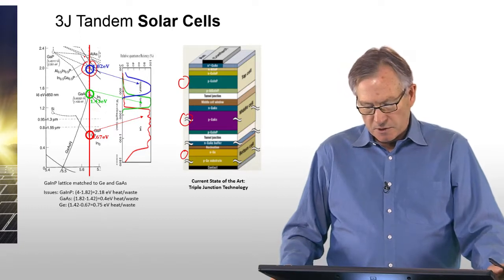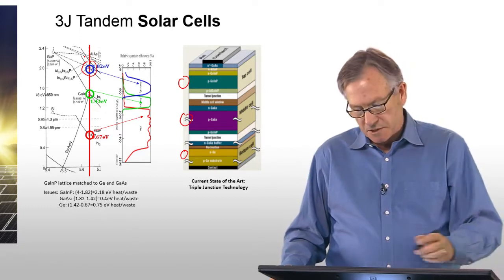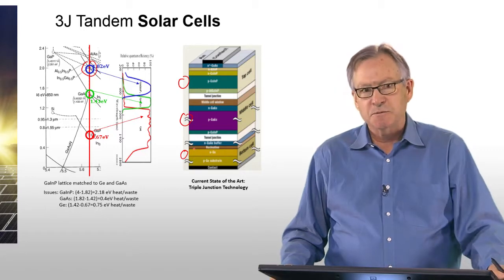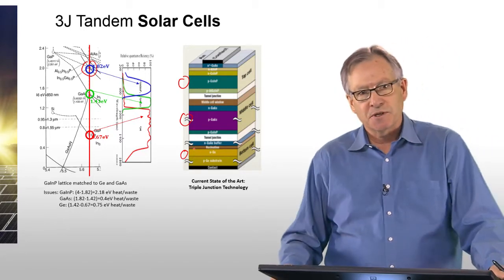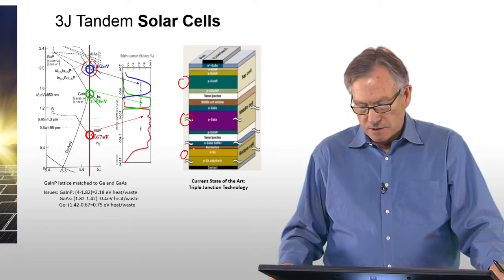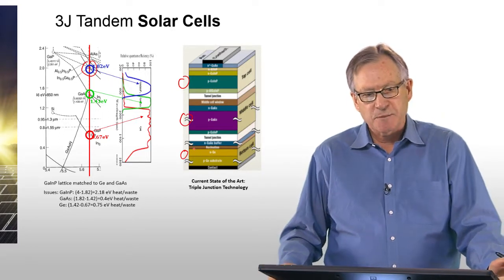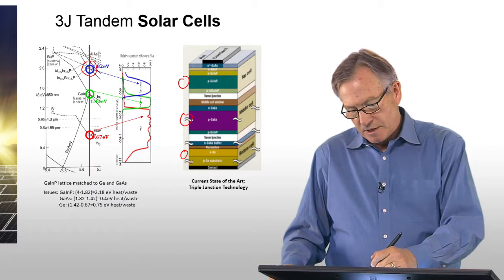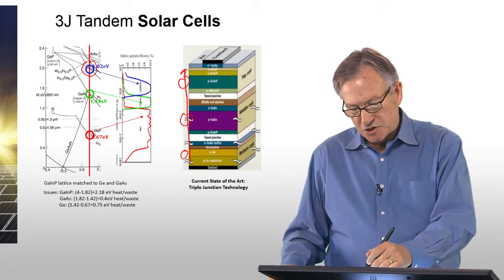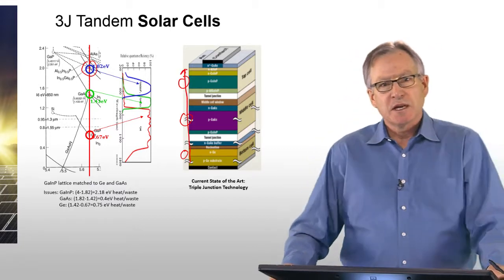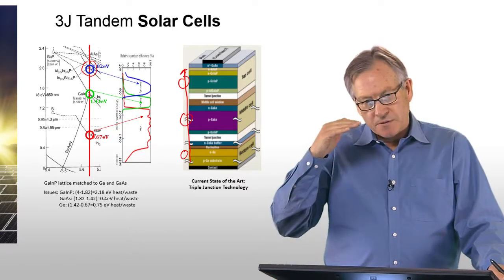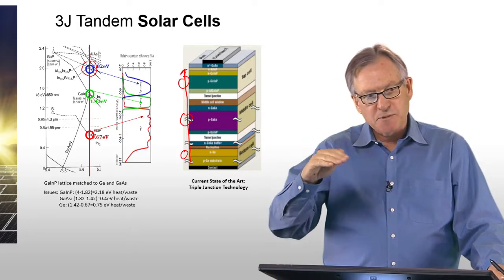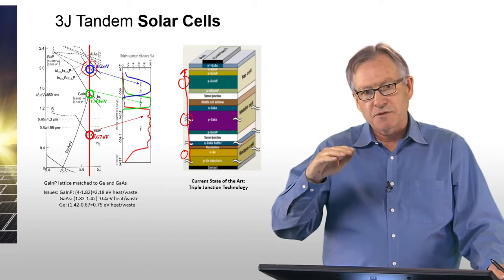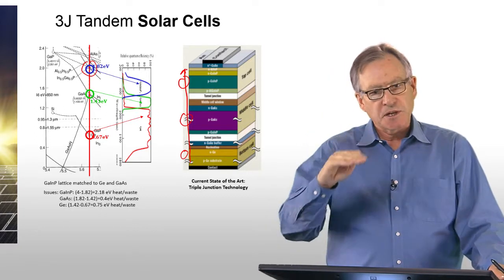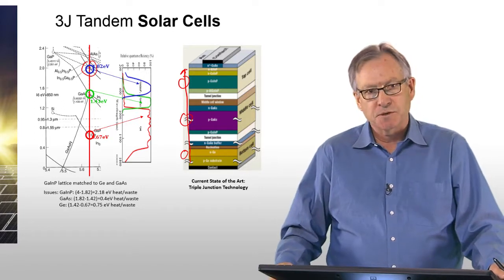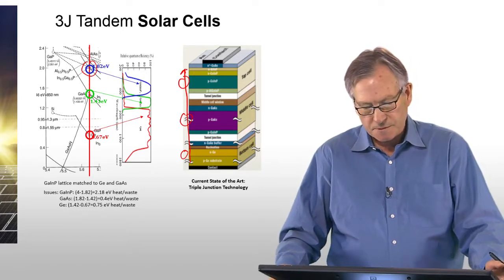Now, these materials are in particular chosen because they are lattice matched. And what I mean by lattice match is they have the same crystal structure and they have exactly the same spacing between the atoms. That's called lattice matching. And that's important because you're going to grow this basically in one shot in a vacuum system. And as you deposit it, if they're not lattice matched, you have thermal mismatch, and more importantly, you have strain that builds up. And the strain eventually overcomes the crystal structure and causes defects to form and degrades the performance.